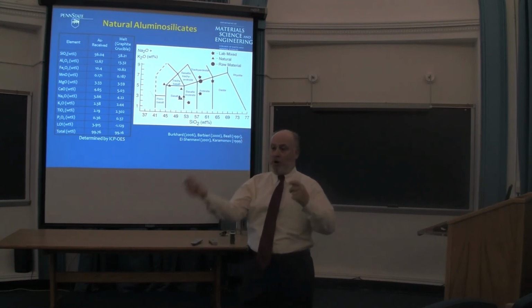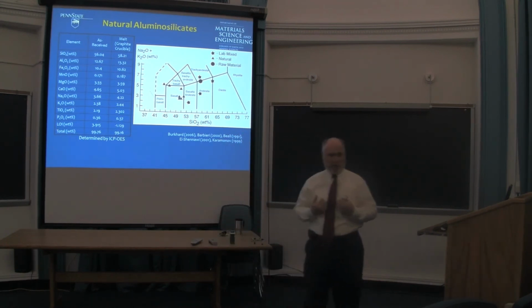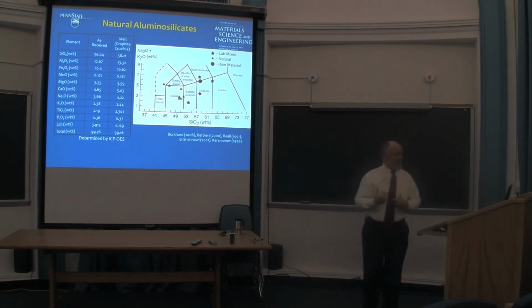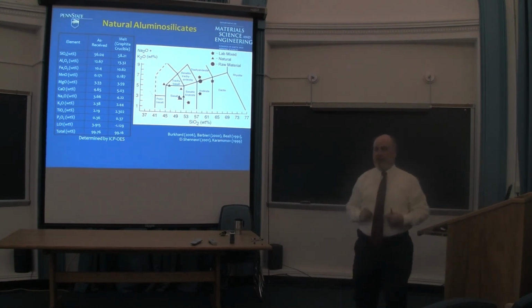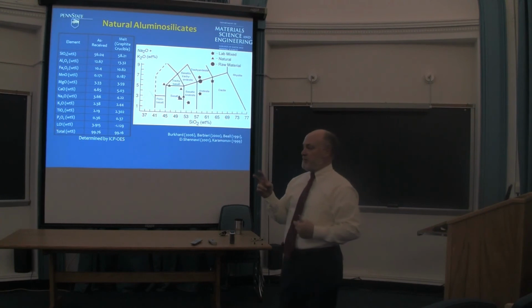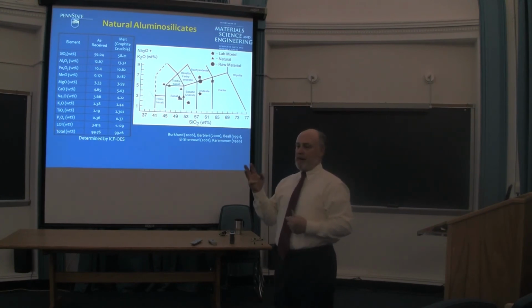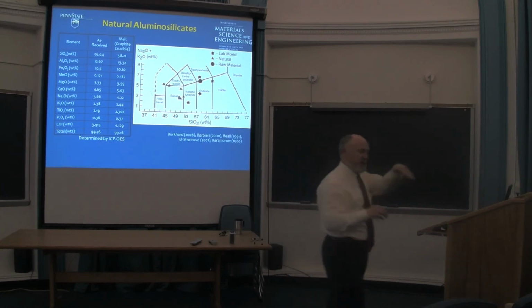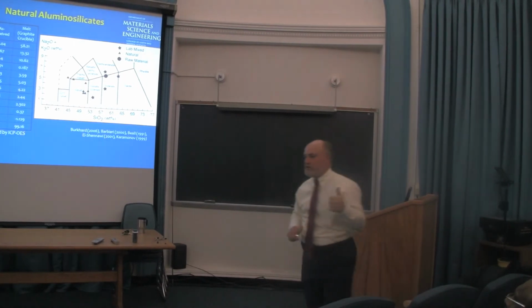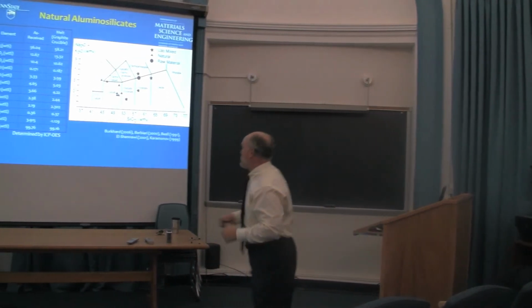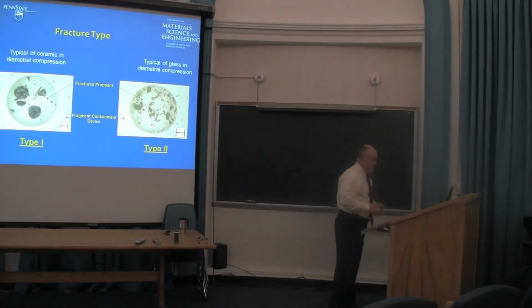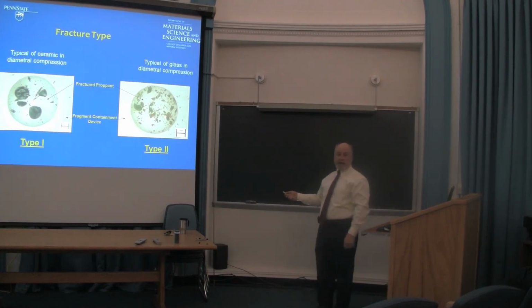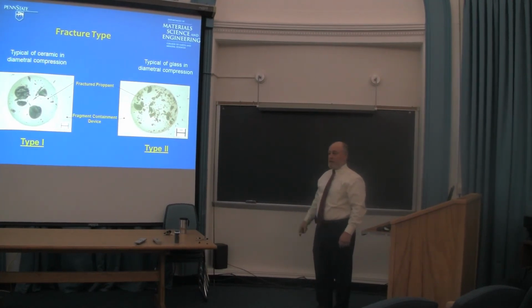Well, if you control that devitrification process, which we do with our furnacing, you can control what crystalline phase comes out, how much of it comes out, and what shape it is, and how it's interconnected, which in turn then interacts with any crack that will propagate through the material, increasing the fracture toughness, thereby causing the stuff to fail like that instead of that. Okay? That was the whole approach, so we did that.